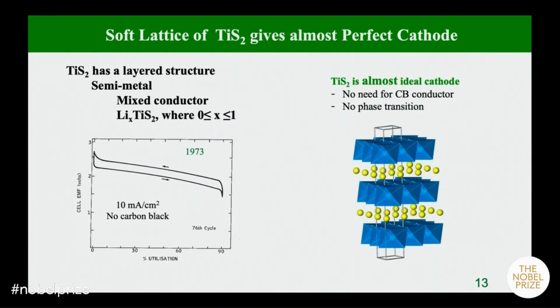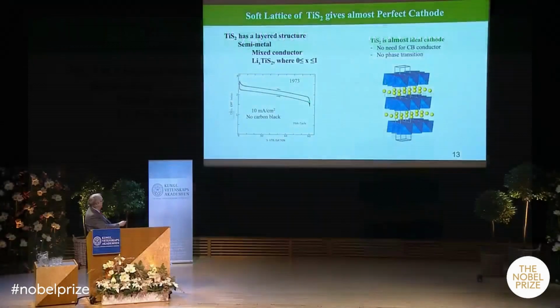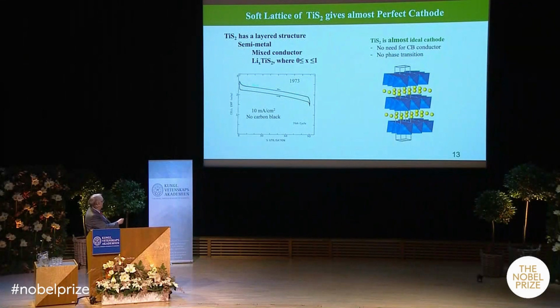Here are the lithium ions, and this would be TiS2. This is a semi-metal. Now, I just call it a metallic conductor, so it's a very, very good electronic conductor. So you don't have to mix any carbon like you do in most materials. And this is a typical discharge curve. It goes down because we're filling the conduction band up. Then when you recharge, you follow exactly the same curve.